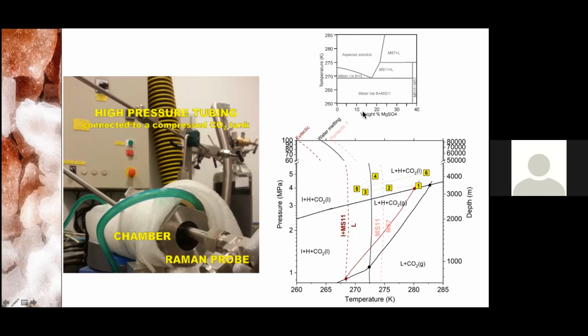In the case of the magnesium sulfate water system, you can have meridianite if you crystallize the phase with 11 molecules of water, or epsomite if you crystallize the magnesium sulfate with 7 molecules of water. But you also can crystallize with 6, with 4, with 1, or you can have also amorphous phases with 3.5, 1.5.